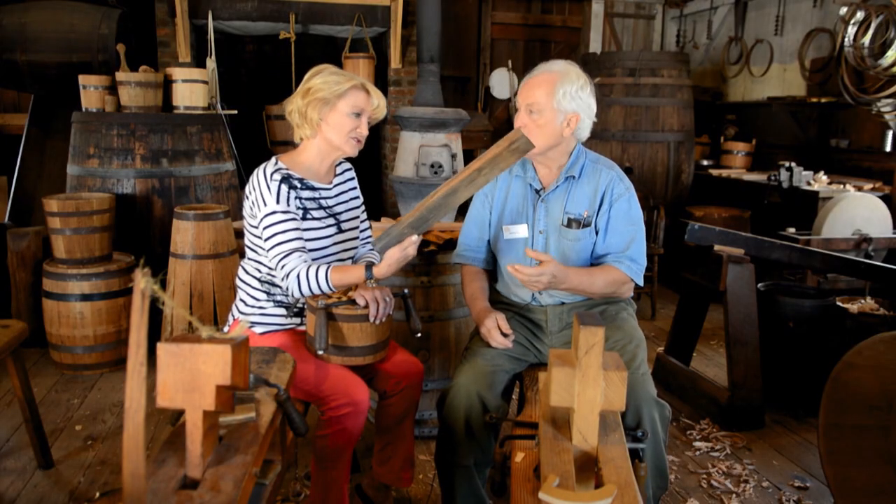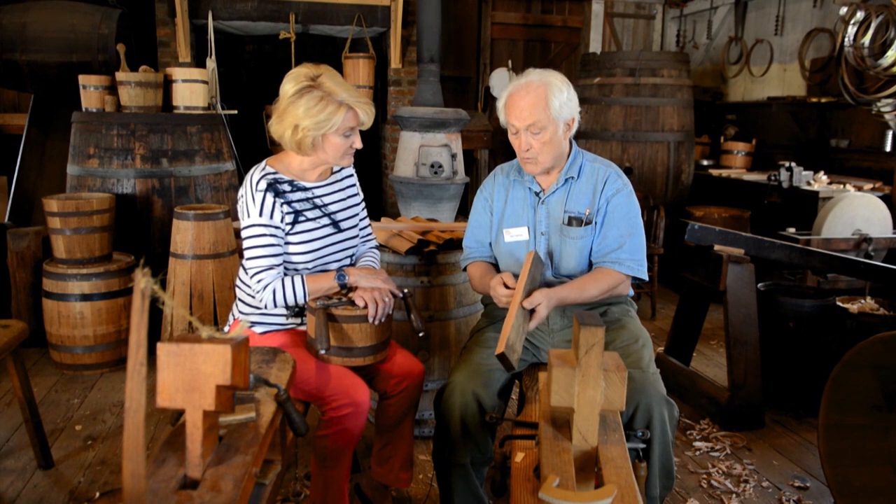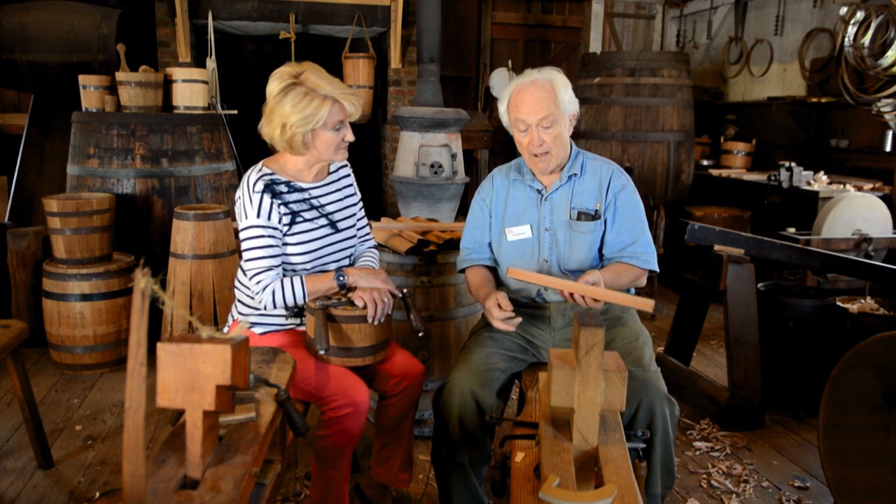Does it matter what kind of wood it is? It depends — different kinds of wood for different contents. This is red oak. Red oak wouldn't work for carrying liquids because it's too porous, so white oak is what we generally use for liquids. I've split this up, left it outside to season for a year — the rule of thumb is a year per inch of thickness. Now I've brought it in and started carving them, putting the arc of the outside of the container on this bunch.